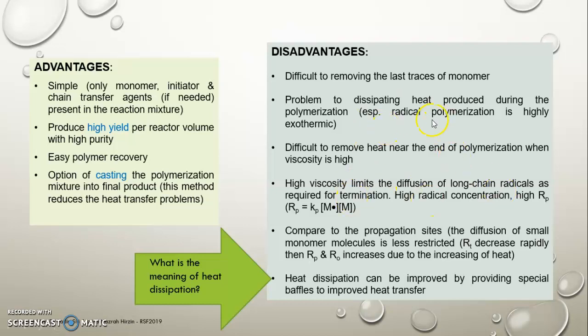High viscosity limits the diffusion of long chain radicals as required for termination. High radical concentration will produce a high rate of polymerization. Compared to the propagation side, the diffusion of small monomer molecules is less restricted, so Rt decreases rapidly, then Rp and R0 increase due to the increasing heat. Heat dissipation can be improved by providing special baffles to improve heat transfer. You can refer to the notes on chain polymerization, where I put the equation for the relationship between Rt, Rp and R0.